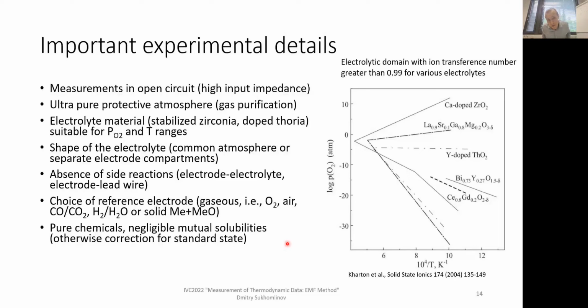Then absence of side reactions is also crucial. As was said earlier, often we cannot connect lead wire directly to electrode because of this issue. We need to find some intermediate contact material which will solve this side reaction problem. Another possible side reaction is reaction between sample and electrolyte. For instance, iron oxide is known to react with zirconia, at least at elevated temperatures.